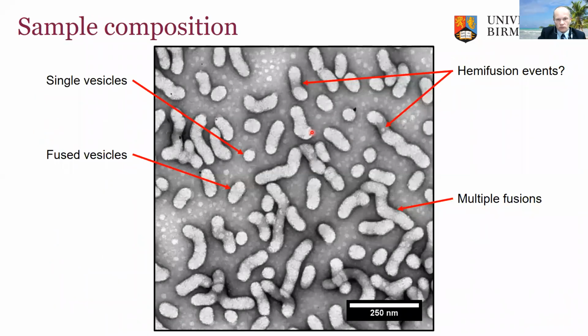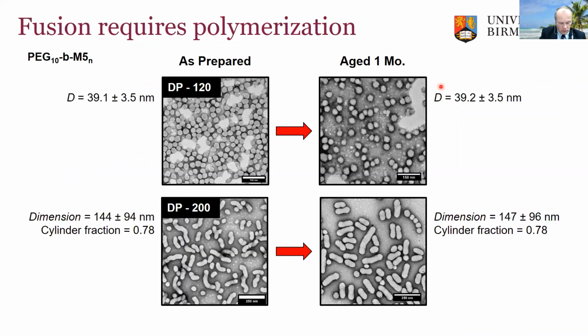So if we look in a little bit more detail at these images, perhaps you can see some fused vesicles, some single vesicles, and vesicles that have undergone multiple fusion events, and also some potential fusion events. So one of the things we were interested in, given the strong indication that we're getting fusion, was when fusion was happening. Was it happening post polymerization or during polymerization? So one of the things we explored, and we checked, was that the fusion basically requires polymerization to occur.